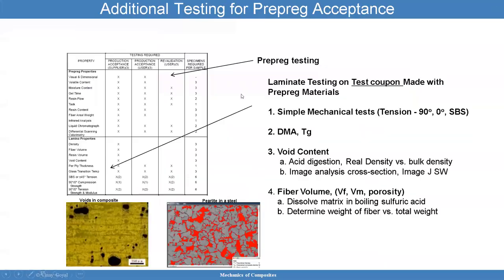So one of the topics I brought up was glass transition temperature. We want to make sure that's clearly understood. The glass transition temperature is a temperature range where the polymer substrate or the resin changes from a rigid glassy material to a soft material, not melted. We're not talking about melting here. And that's usually measured again through the DMA and is measured in terms of stiffness or modulus, okay? And it provides a lot of information about the material and how good the quality of the material is.